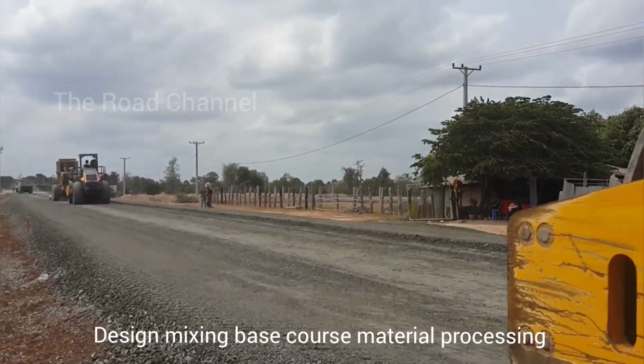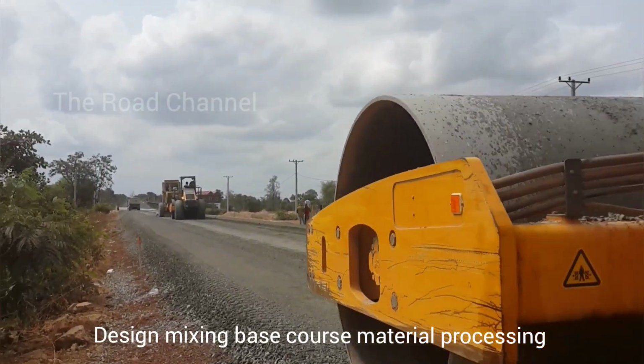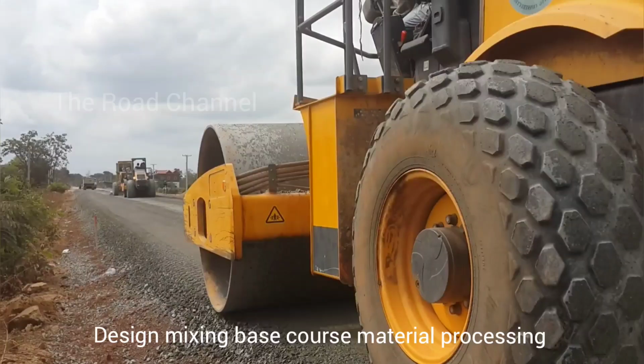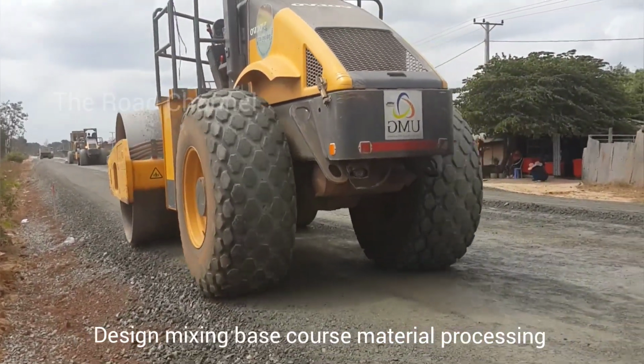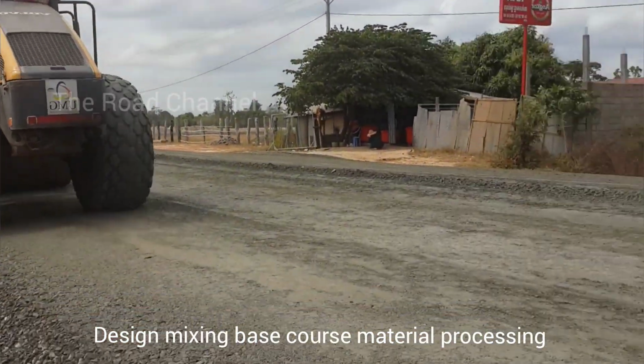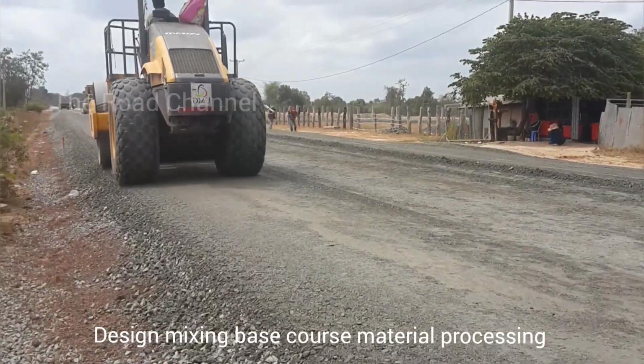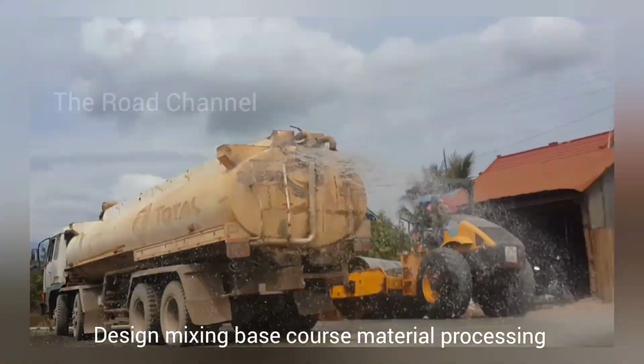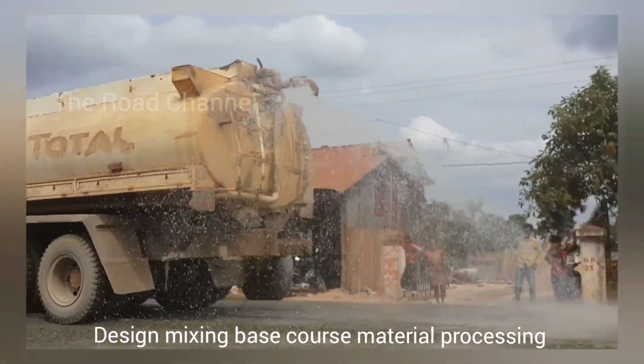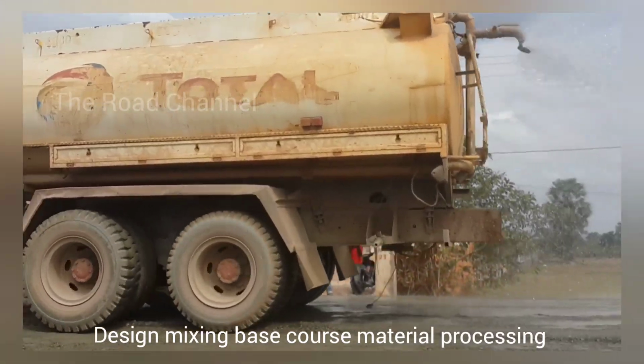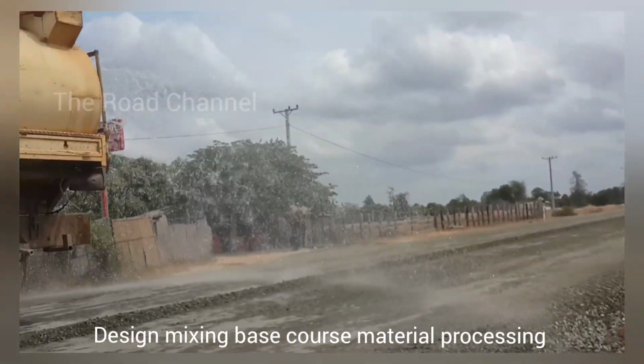7. Field testing. Once the trial mix meets the specifications, produce small test sections in the field to confirm that the material behaves as expected under real construction conditions. Perform field compaction testing using a nuclear density gauge or sand cone test to ensure that the mix compacts well and achieves the required density.